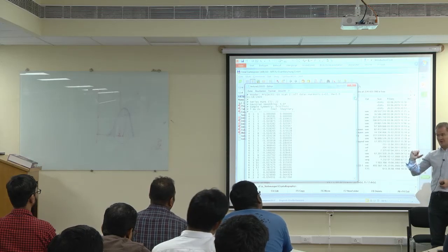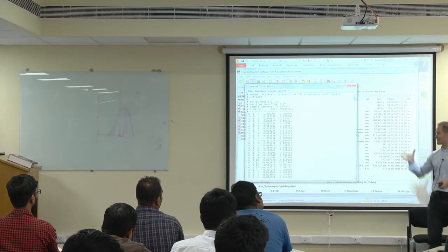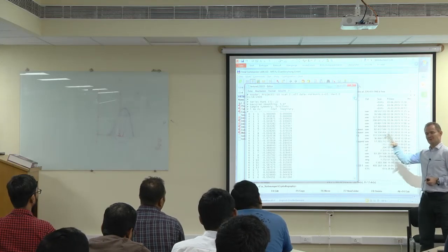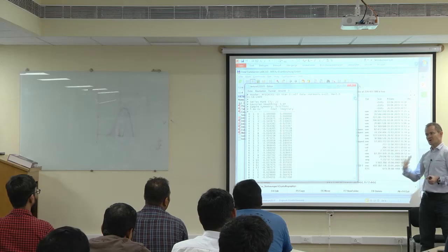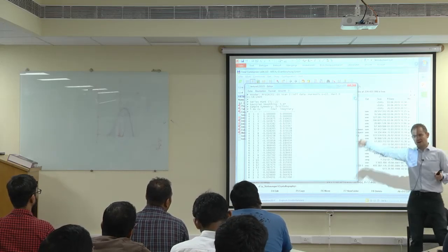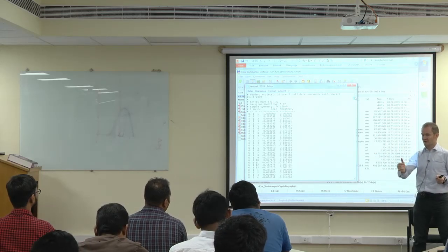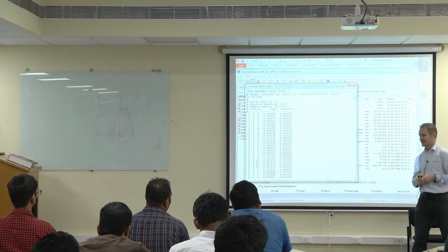Is the texture sharpness. So you need to get a little bit of experience, and you need to compare your measured texture with the calculated texture to make sure, okay, I see all the major features. Or when I go to a higher expansion rank, it does not become better. Then you can say, okay, I can stop at 16 or at 8 or something like that.